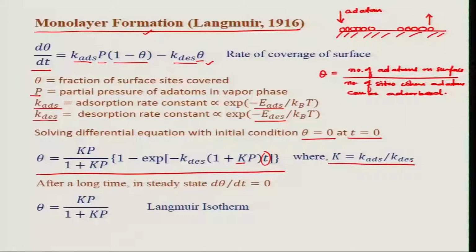Now, we want to know: if we have kept a surface at some pressure P and temperature such that K is the ratio of adsorption to desorption rate constants, after a long time we will have a steady state because some of the atoms will be adsorbed and some will be desorbed. So, it will reach a steady state, and at that steady state the fractional coverage would be given by this.